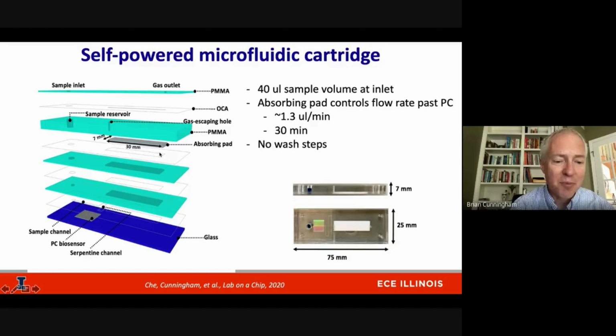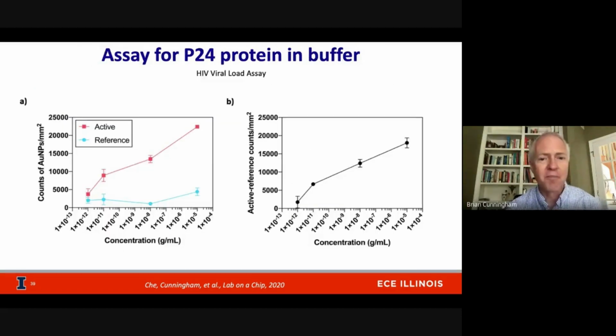There's an absorbing paper pad that draws the samples through at a rate of around 1.3 microliters per minute. So a 40 microliter droplet sample goes through in about 30 minutes. But the user doesn't have to do any other wash steps. Just add the sample in and then wait for the nanoparticles to get accumulated. We used this first in the context of doing a viral load counting assay, called an antigen assay, for a protein called P24 used to perform HIV viral load measurements.